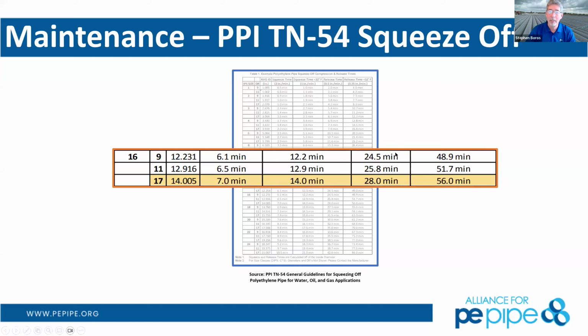that release. So normal release time above 32 degrees will be half inch per minute, resulting in almost 25 minutes just the release time on that 16-inch pipe. If you're below 32 degrees, you've got to double that again, and you're going to a quarter inch per minute, up to 50 minutes or 49 minutes, to release that squeeze to make sure that you don't damage it. All this is detailed within this document. If you follow those procedures, you're not going to have a damaged pipe and it won't be an issue.